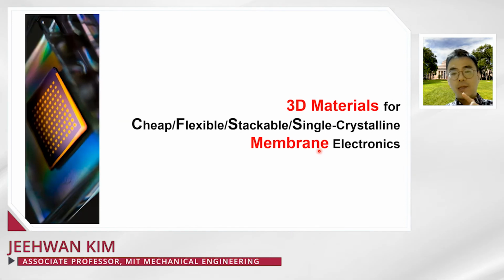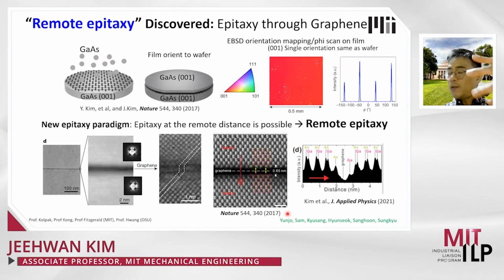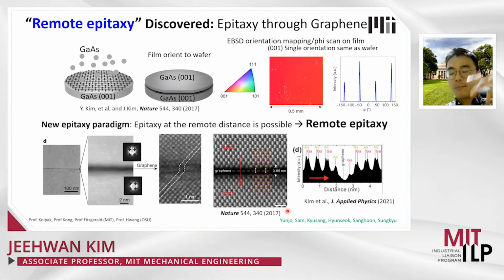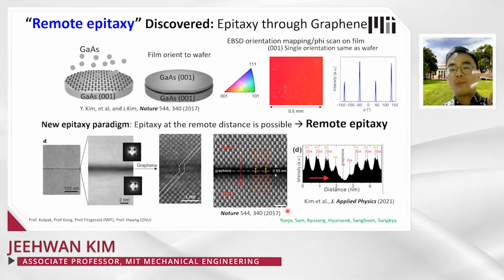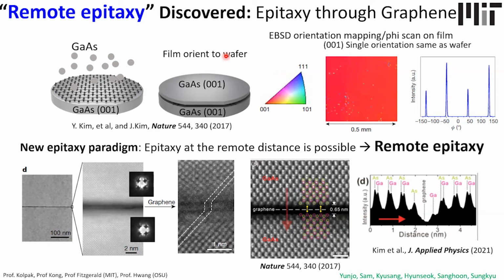Okay, so in the year 2017, we reported a way to produce freestanding single crystalline membranes from almost any source of 3-dimensional materials. The concept is right here. So we invented and announced this new epitaxy technique called remote epitaxy to the world. The method is as follows. So we try to grow a single crystalline material whose chemical composition is similar to the wafer, but while we are performing the epitaxy of the same material as the wafer, we locate a monolayer graphene on top of the wafer. Why graphene is needed? I'll tell you about this later.